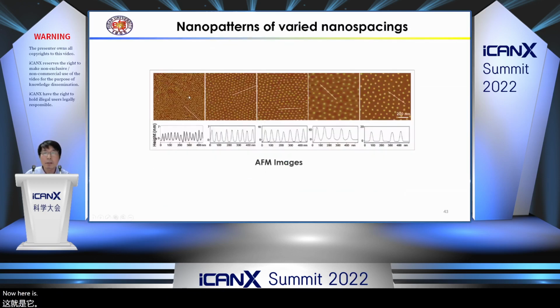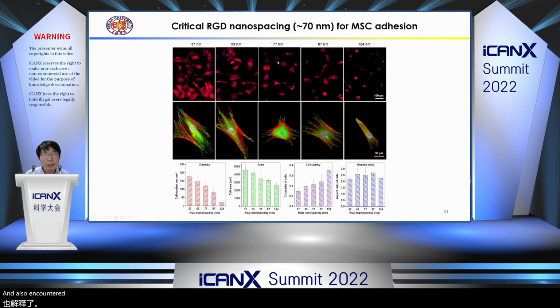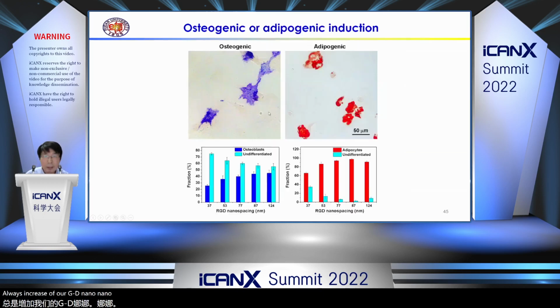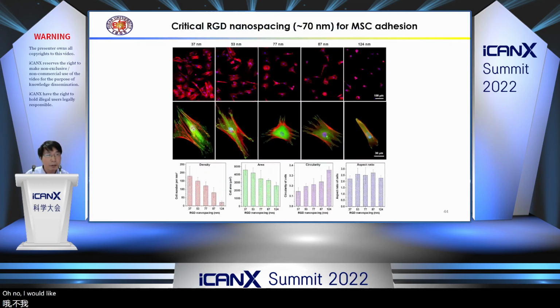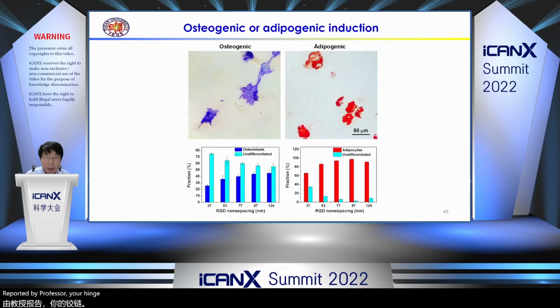Now here are some experimental images of the nanoarray with a series of nano spacings. And we also cultured our cells on a series of nanopatterns. We did find changes in cell adhesion with the increase of RGD nano spacing. I would like to emphasize that the nano spacing effect on cell adhesion was first reported by Professor Joachim Spatz. However, the nano spacing effect on cell differentiation was first reported by our group.